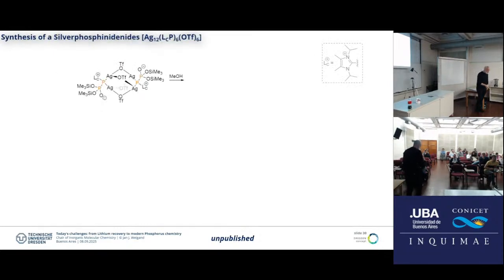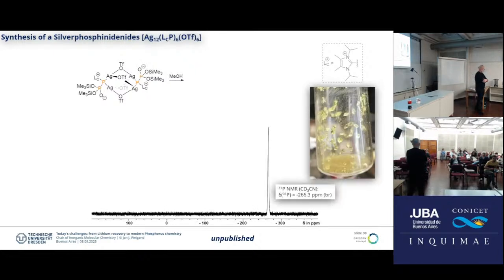Now, the most important one, that's the silver you've seen before. We still have two silyl groups, and we said we can take them off, for example, as alcohol, or with water, as we've done before. Now, if you do that reaction, and you know, if we have the PP bond, we would expect in the NMR our AB spin system, the two doublets. Now, if you plunge methanol into that compound, you get a very weird NMR. It's just a singlet. And you get super big crystals, quantitative yields.